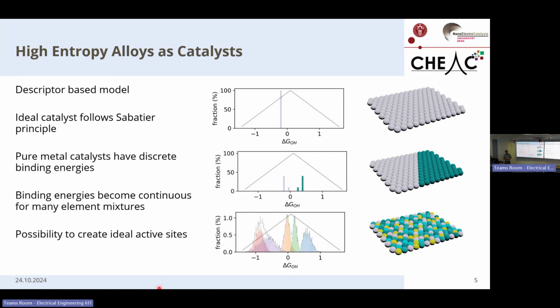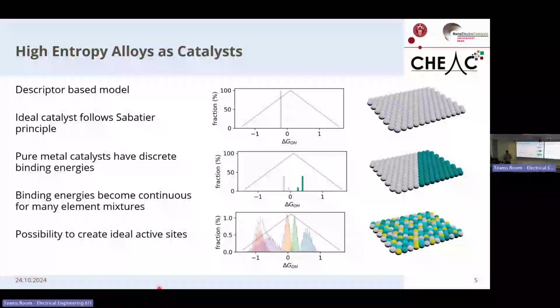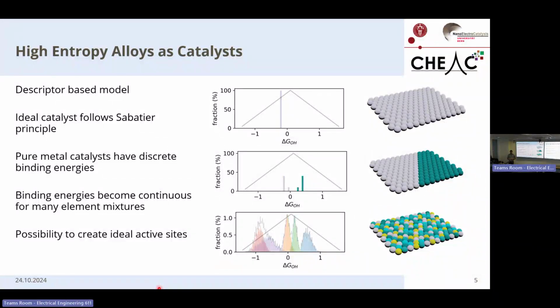So if you now have pure metal catalysts, the binding energies of the intermediates will depend on the catalyst material. And the only way to change the catalytic mechanism and the activity is to change the entire material. But if you now create an alloy, you create new active sites, which are a mixture of multiple elements. And these will have a slightly shifted binding energy towards the reaction intermediates.